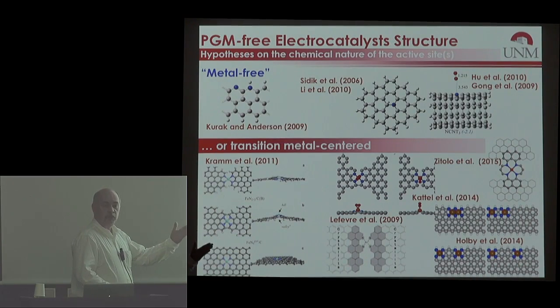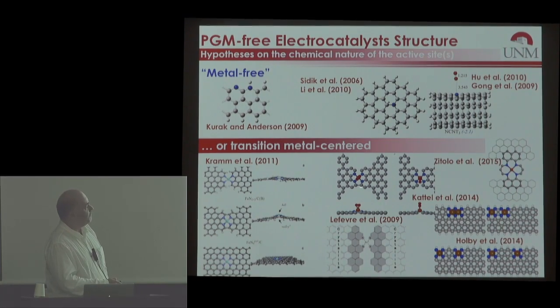So people do think about this catalyst as defects in graphene nanosheets. Whether these defects contain iron or do not, there are two schools of thought, and there are romantics who think that carbon can reduce oxygen to water without using any transition metal. We'll leave that to history, and I belong to the party of realists that think that a transition metal is needed for the coordination of oxygen, at least at the adsorption stage, and I also think that it's needed for the actual charge transfer stage of the electrocatalysis.